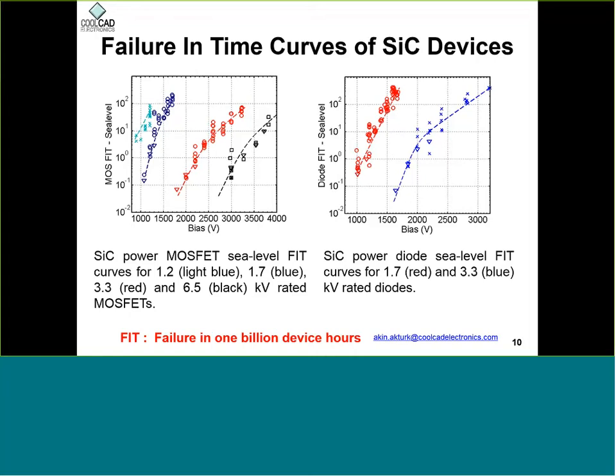So if you look at the plots, these show different silicon carbide power device failure in time curves as a function of bias. If you go higher in bias, you're more likely to fail because the fields are high, and that can give rise to a catastrophic event more easily. Here on the left, I show 4 curves for 4 different voltage rated parts. And on the right, I show the same kind of curves as a function of bias for 2 different silicon carbide devices. The higher the voltage rating, the higher the bias at which it starts failing. And also, once the failure starts, as you increase bias, the failure rates will increase exponentially. That's the general rule of thumb.